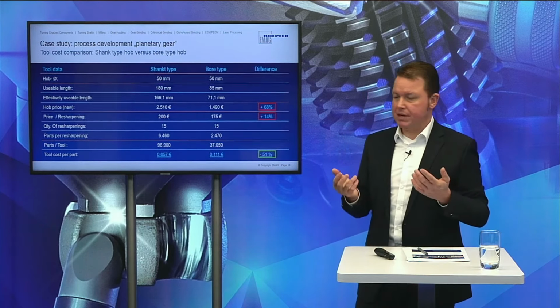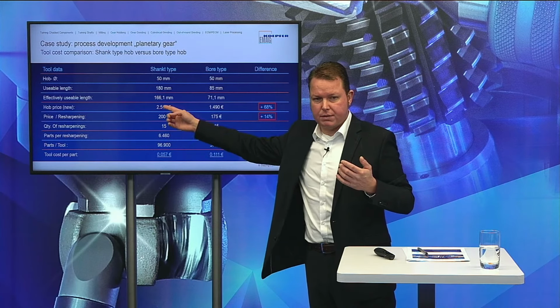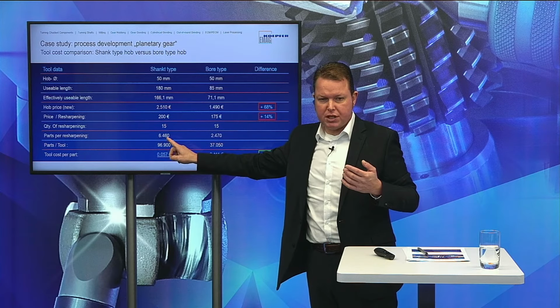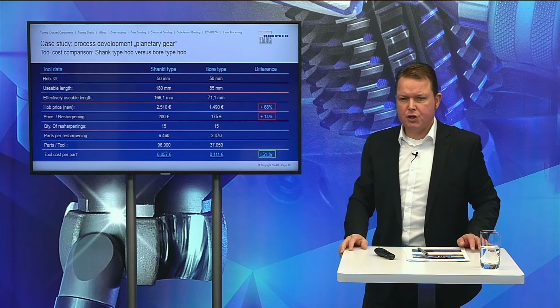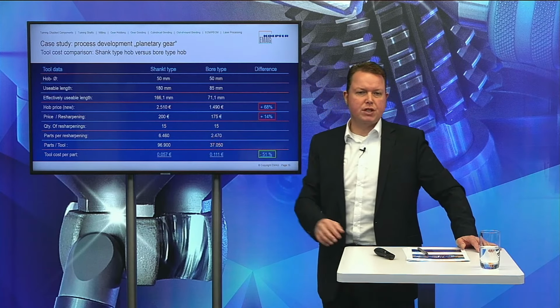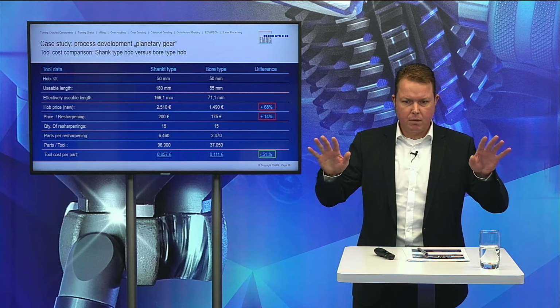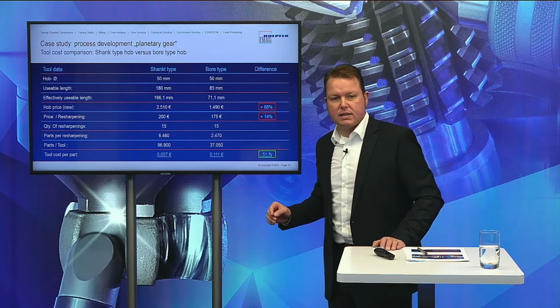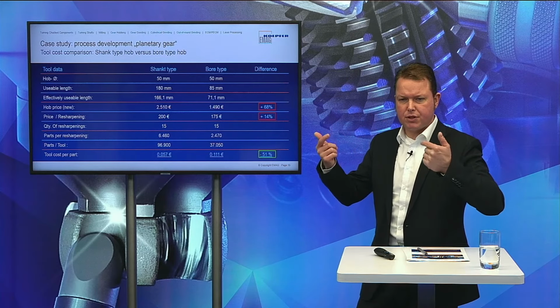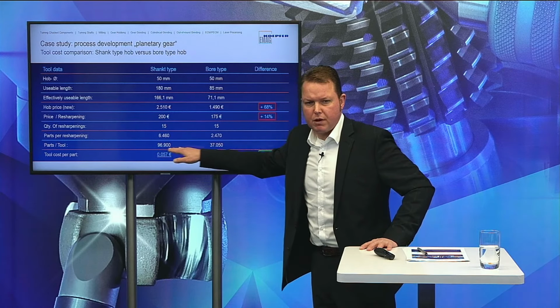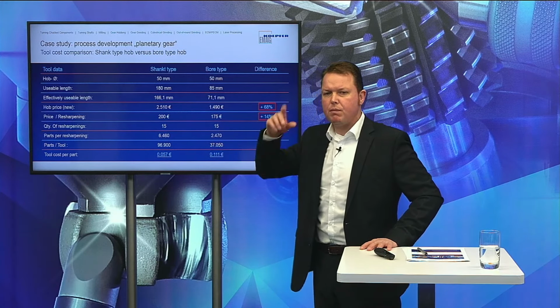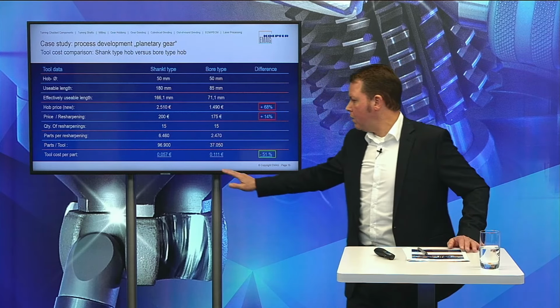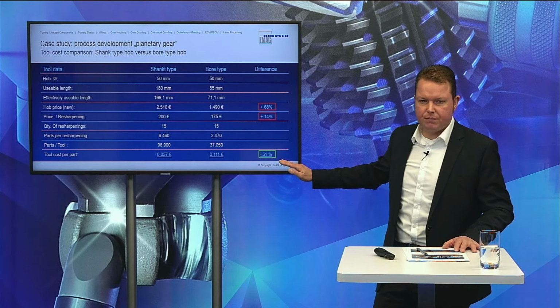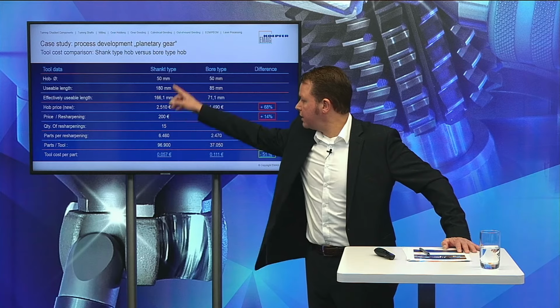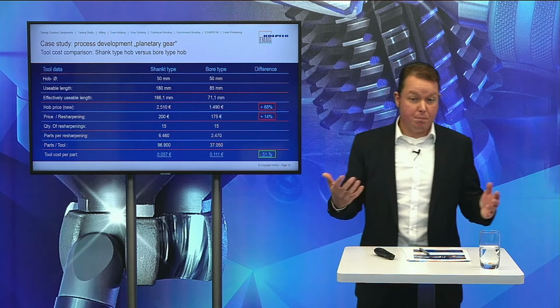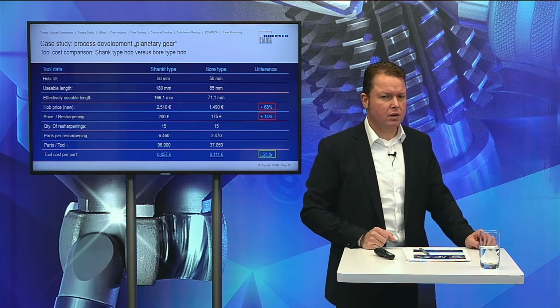Both hobs can be resharpened roundabout 15 times. So parts per resharpening, however, is way higher with the shank type hob as we have the higher shifting range. Accordingly, we can machine 6,500 parts until we have to resharpen the shank type hob, and only 2,500 until we have to resharpen the bore type hob, and this with the same meter per hob tooth tool life. So at the end, if we break down all the cost for maintenance and purchasing on the parts, this hob gives us nearly 100,000 workpieces, the other one 37,000 workpieces. So if we divide all the cost by the number of workpieces machined, we see that the ratio is roundabout a reduction of 50%. So we have 6 cents on the shank type hob and 11 cents on the bore type hob. It's impressive how we may reduce the cost for tools.